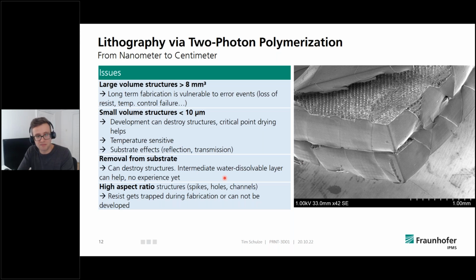And for that reason, we figured out that critical point drying is quite helpful. And also in this case, structures can be a little bit temperature and resist sensitive, and it's a lot of trial and error. And in case you have ideas for printing something, I guess we can figure something out to address those issues. And in the meantime, reflectance can also be an issue when the structure is really close to the substrate, and transmission can be an issue if the laser intensity, for instance, is too high with certain substrates. It can heat up and form bubbles and stuff like this. So for specific structures, we need to do some parameter testing to figure it out. And also the removal of parts can be quite complicated.